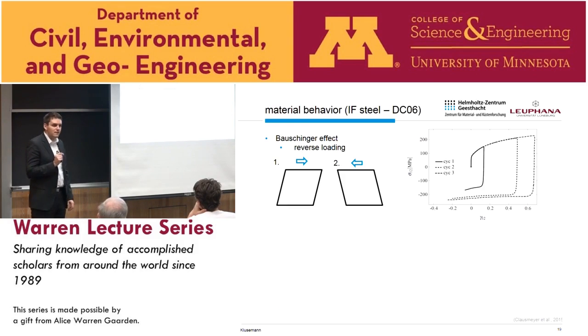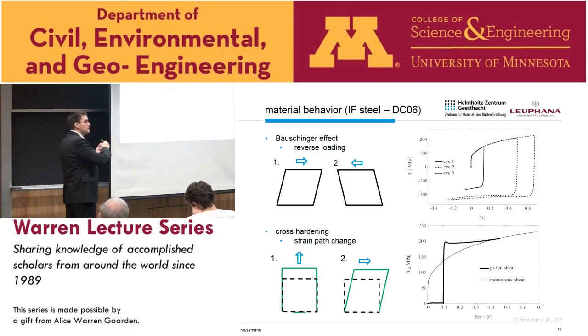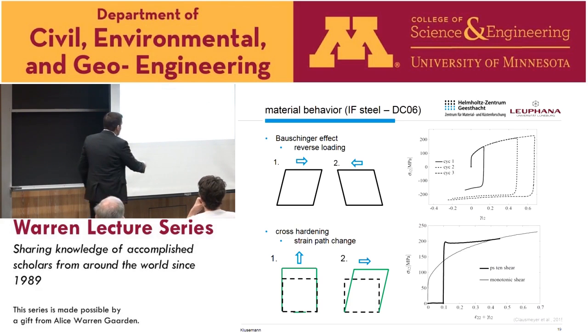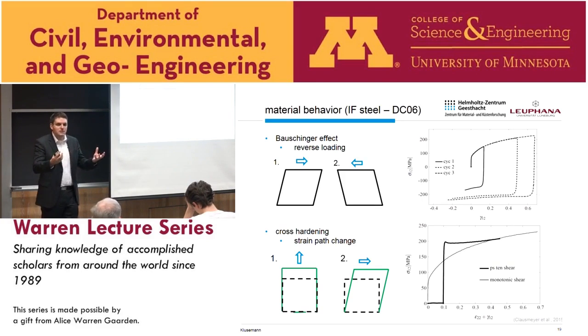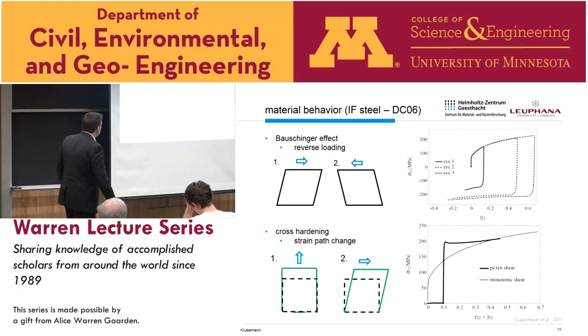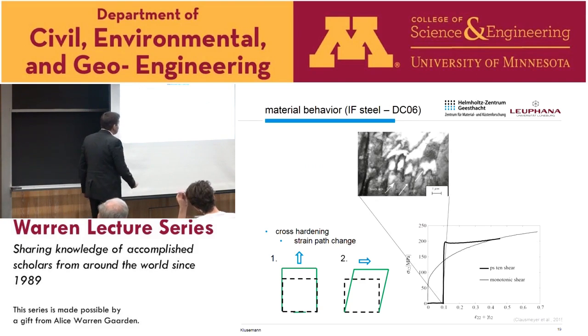This is the Bauschinger effect, and additionally these kinds of materials show so-called cross-hardening behavior. When you have an orthogonal strain path change, so you first make a plane strain loading, then apply a shear loading onto this, you see this kind of behavior. So what does it mean? Well, you see here a strong stress overshoot. This one here is the classical monotonic shear loading response of this material. However, when I first do a plane strain tension loading and then a shear, I have a much higher yield strength. Well, what is the reason for that?